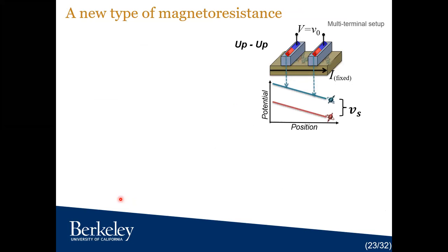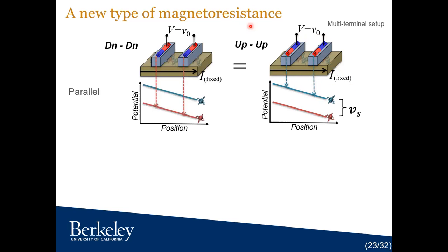Another thing I want to show is another prediction from my PhD. Now let's think about the same thing, but with two magnetic contacts. Let's keep the current flowing in the spin orbit material fixed. When both the magnets are in the up direction, both of them will probe this blue curve, and the voltage difference will be just this offset voltage due to the ohmic drop within the channel. If you reverse both of them, so both are in the down direction, both will measure this red curve and measure the offset voltage. So these are parallel states and they are equal.